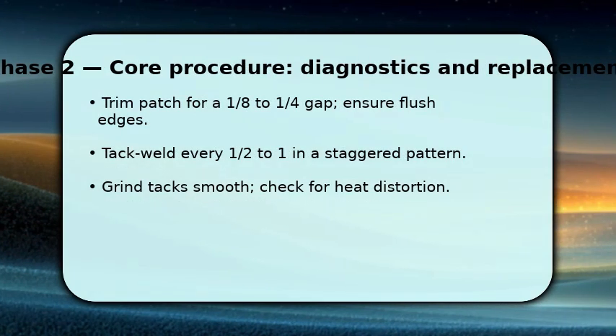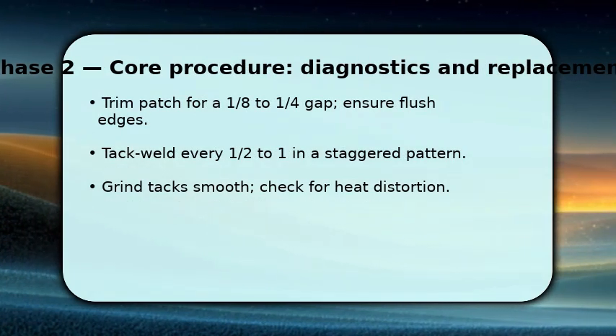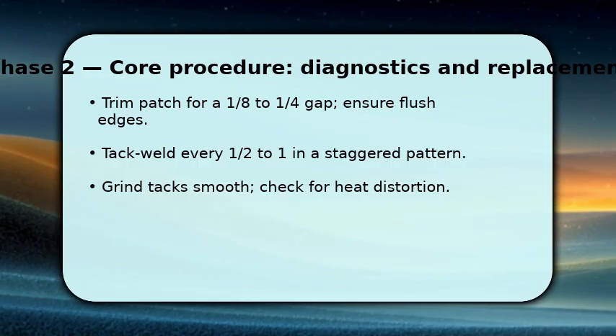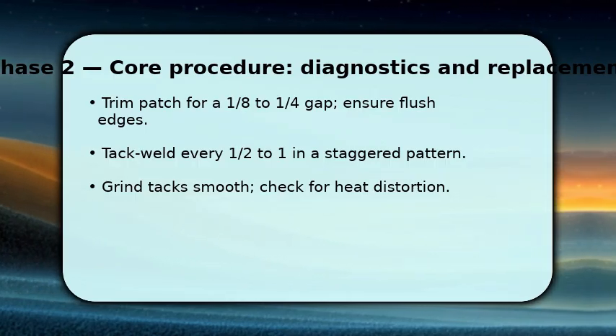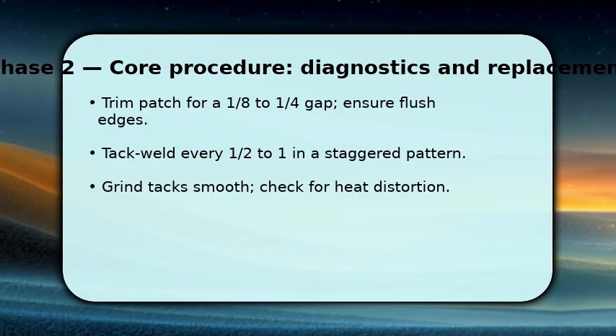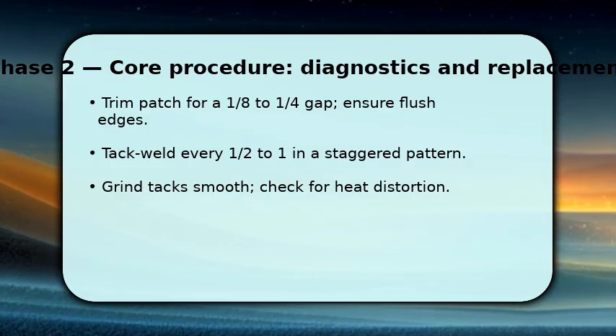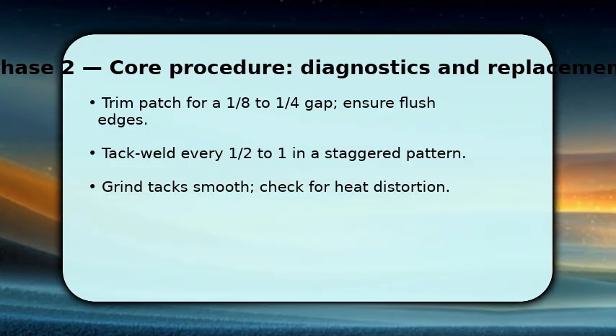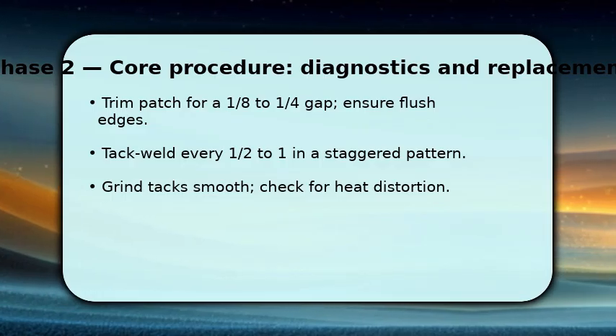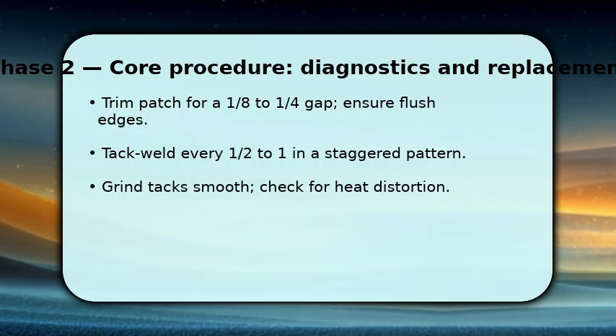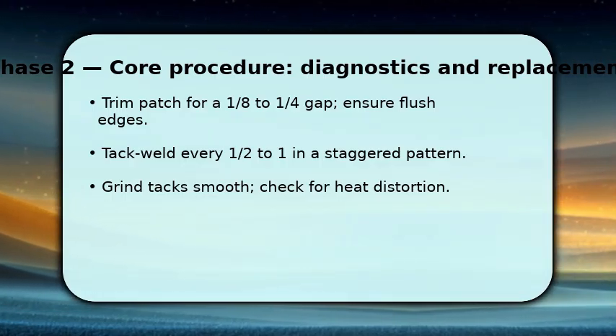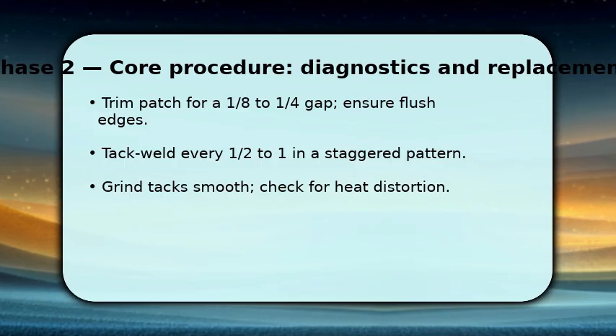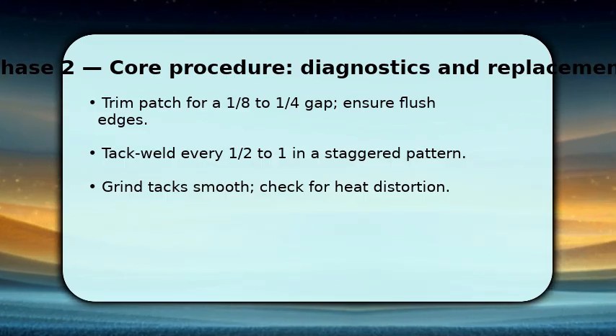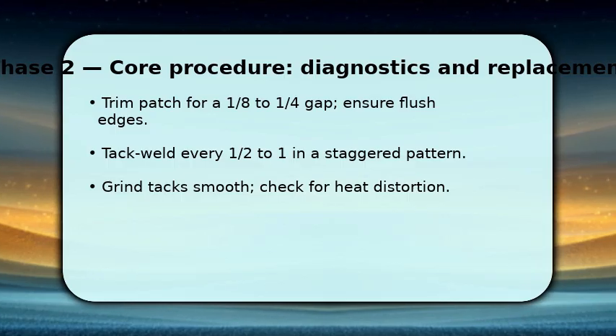You fit the patch and control heat to avoid warping. Cut the patch to leave a small gap of about 1/8 to 1/4 inch for proper weld penetration. That gap also reduces burn-through. Tack weld the patch in a staggered pattern every 1/2 to 1 inch to pull metal evenly. Let the metal cool between tacks, then grind the tacks smooth. This prevents heat buildup and keeps the surface flat. Make sure to check alignment and reclamp if distortion appears.